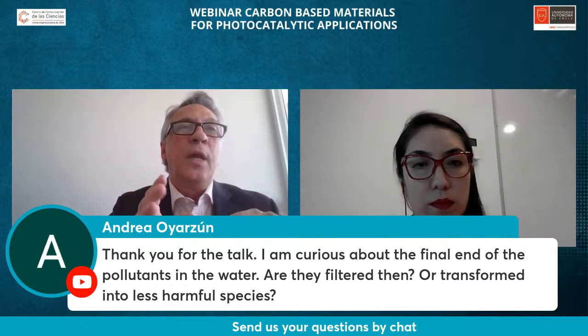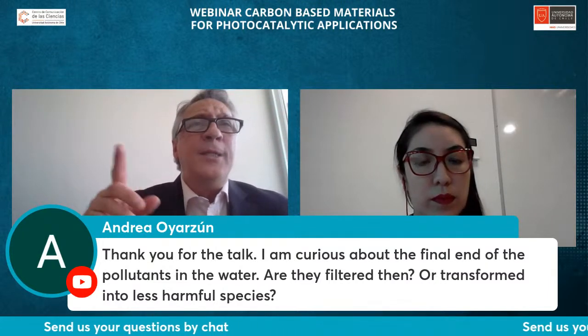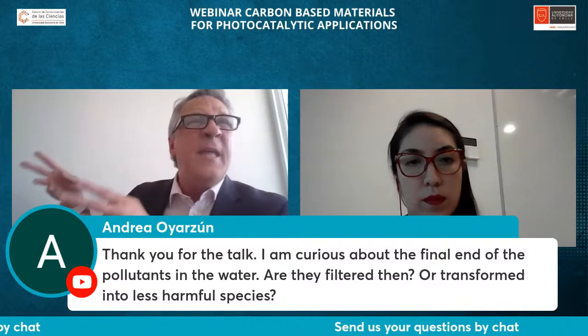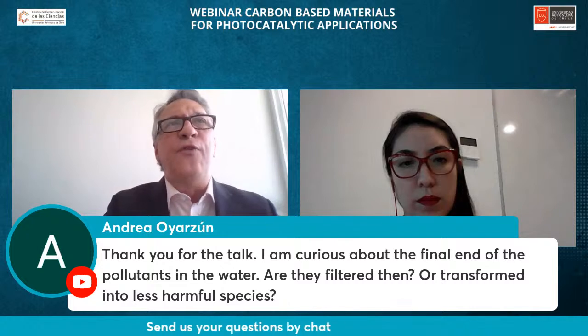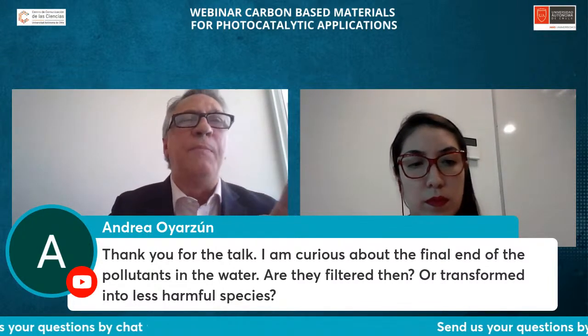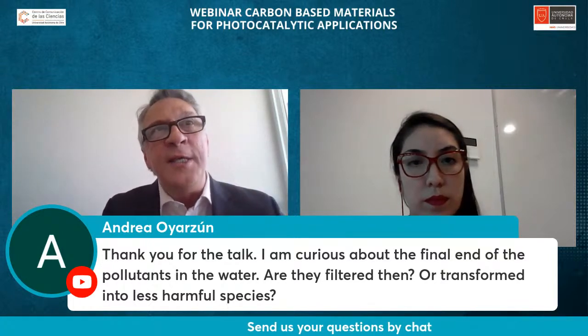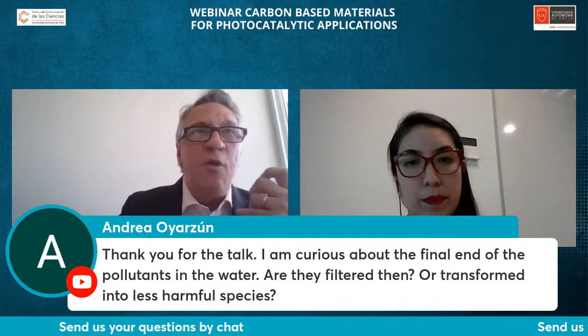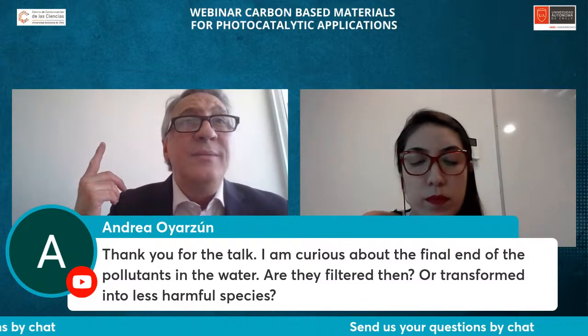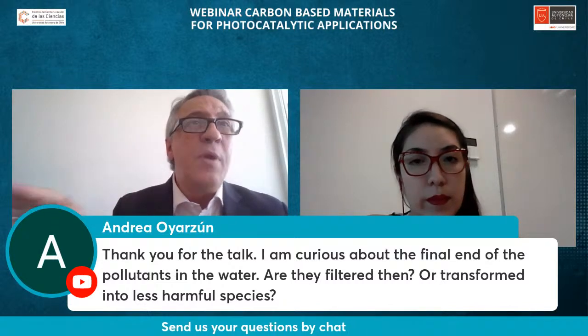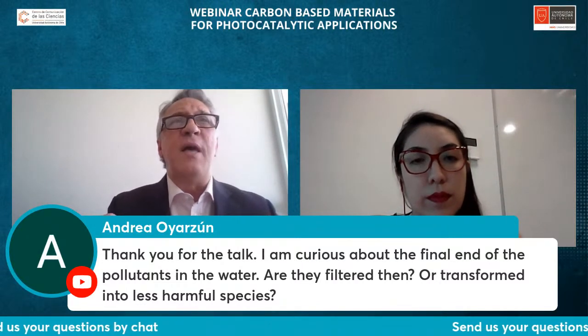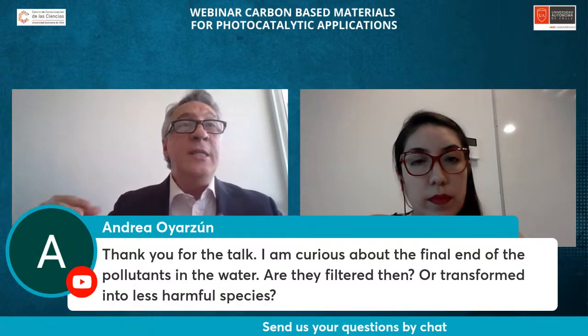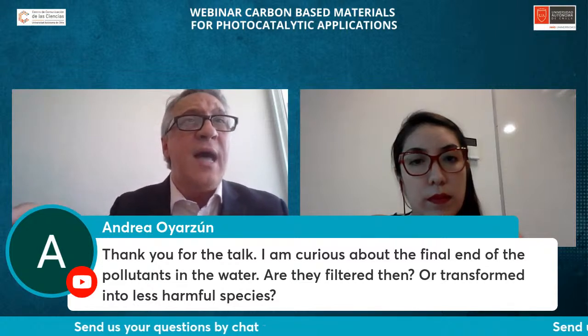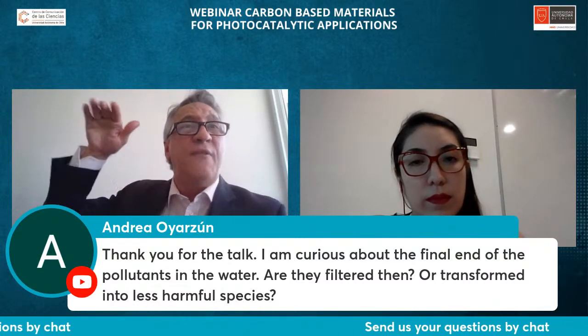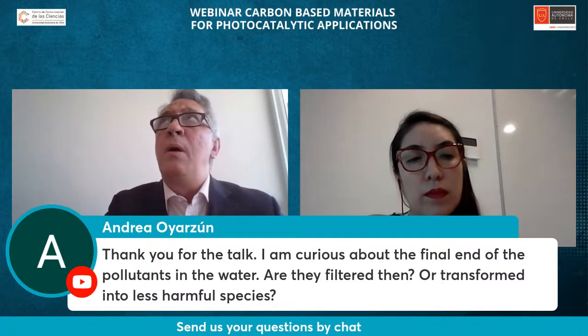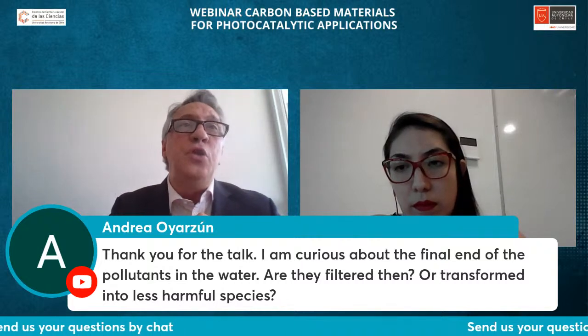So you start with a pollutant, and during the degradation, the final products are the mineral ones. This technology is also called photomineralization, because all the organic products are converted into mineral products. For instance, if you have phenol, for one mole of phenol you will have 6 moles of CO2, and the rest is water. But if you have, for example, an azo dye with nitrogen or sulfur, in addition to carbon dioxide and water, you will have mineral acids. But mineral acid is not a problem because you can filter with a filter of carbon. So that is another important advantage of using carbons.